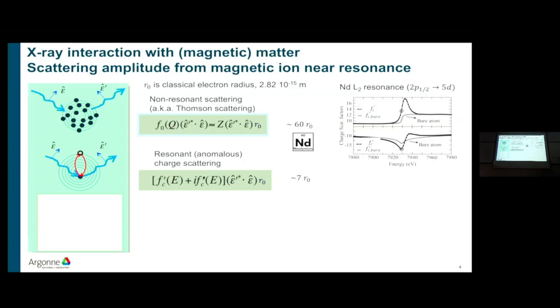But when you put that atom in a solid, this valence electron or valence empty state is not just one atomic orbital, but it's a band in the solid, and this cross-section is modified, so it goes much higher. So instead of 2, it's actually about 7. So it's 10% of the non-resonant part. But there is no sensitivity to the magnetism here. This is just sensitive to the empty density of states, or the number of holes you have in the orbital in this intermediate virtual state.